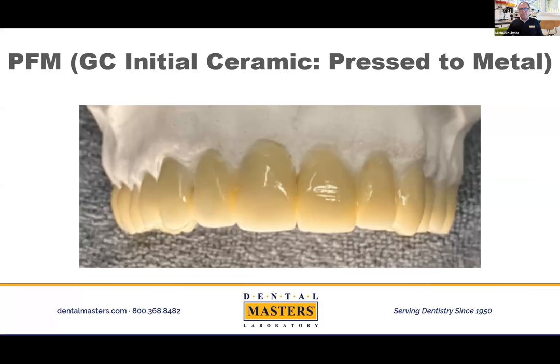PFMs, there's still a place for PFMs. These PFMs are not hand stacked. They have been put onto a selective laser melt substructure, SLM printed by our colleagues at Argen, to which we have done a wax overlay, a milled wax overlay that we have then pressed, like we can press Emax, Empress, LiSi. These are pressed to metal restorations.